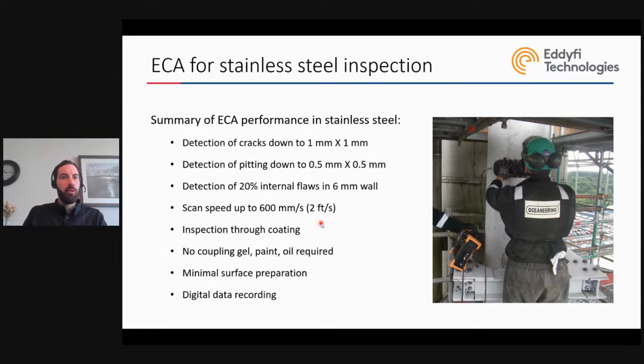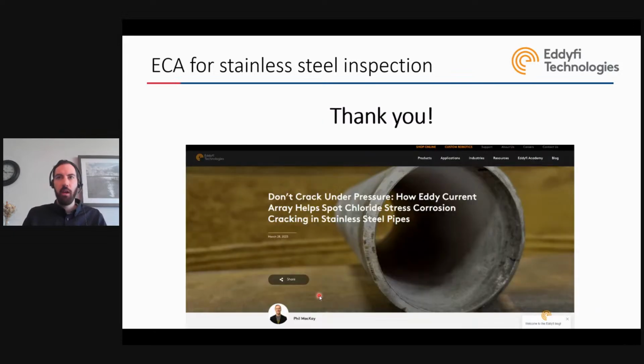The scan speed is up to 600 millimeter per second. You can inspect, as we showed, through coating. There's no requirement for paint, oil, gel. There's no consumable with this probe. So you put the probe directly in contact with the steel or directly in contact with the coating, and you start your scan. Minimal surface preparation, depending again on the coating thickness, and you get digital data of the C scans.